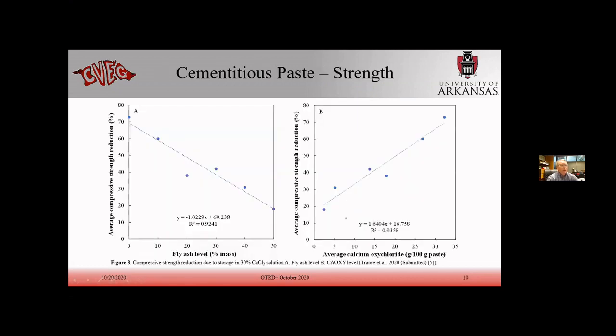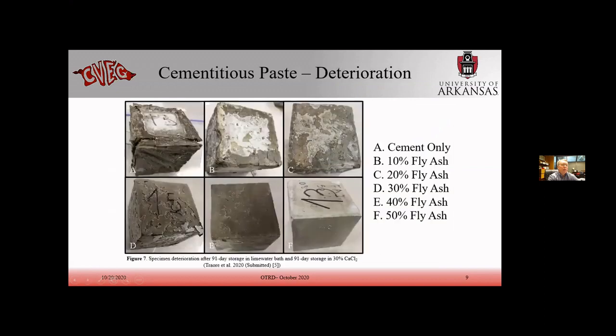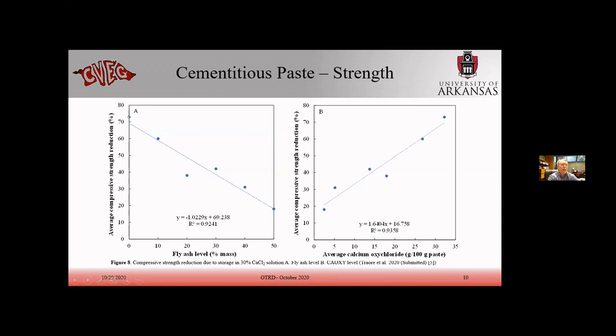It just shows the reduction in strength, and also the amount of calcium oxychloride per compressive strength reduction. On the left, we have our average compressive strength reduction. The first picture back here, you can see didn't have a whole lot of strength left at the end. We had about a 70% reduction in compressive strength, and it follows a general line.